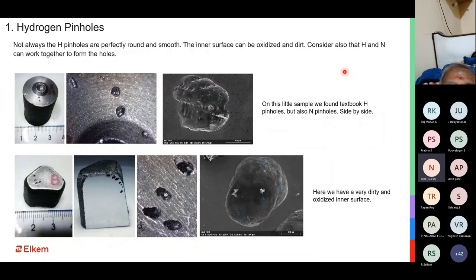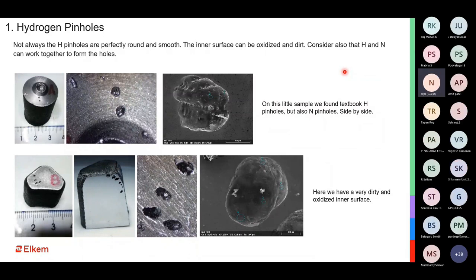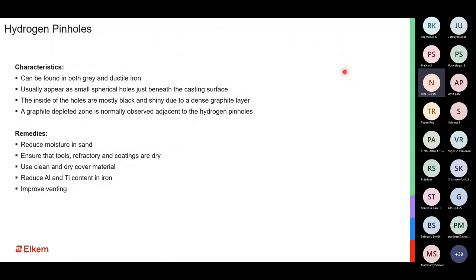Hydrogen pinholes as such are not completely round and smooth. They can have some amount of oxidation, and some roughness in the surface. That is the initial indicator of how you can classify a pinhole as a hydrogen pinhole. Of course, this type of pinhole can be found in both gray and ductile iron. It appears as a small spherical hole and may not be present on the casting surface, but would be just below the casting surface in most cases, and can be revealed during machining, sectioning, etc.